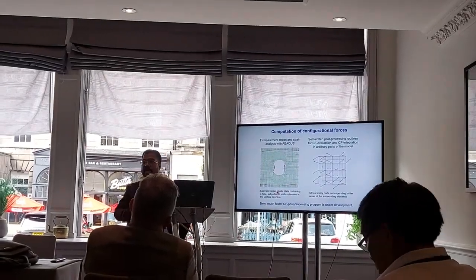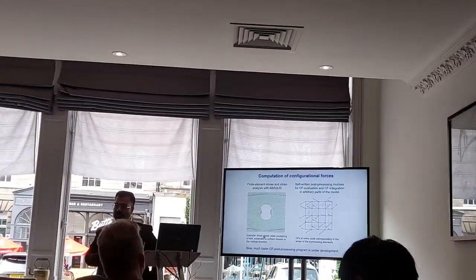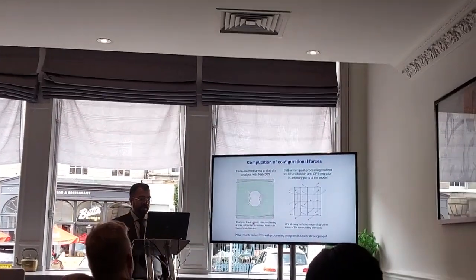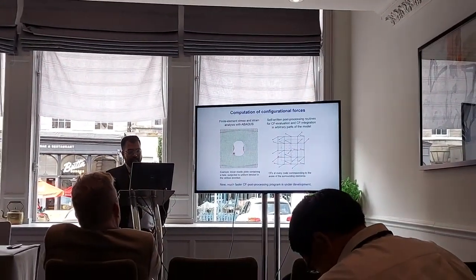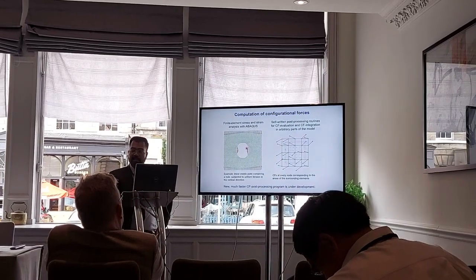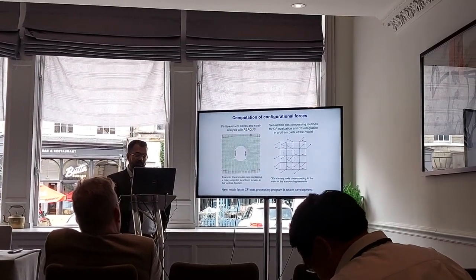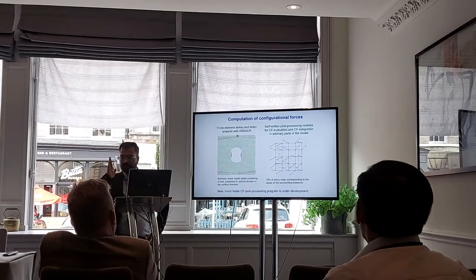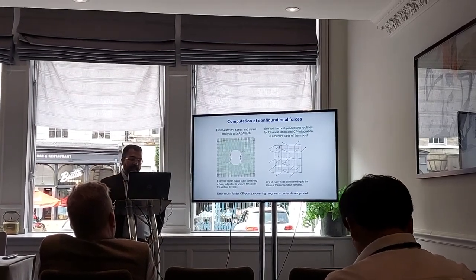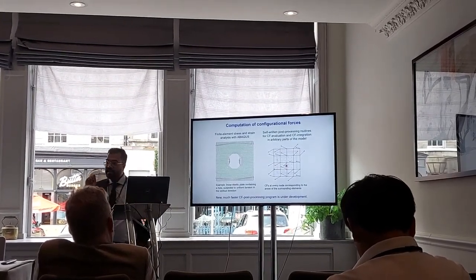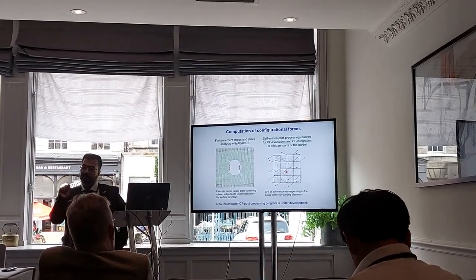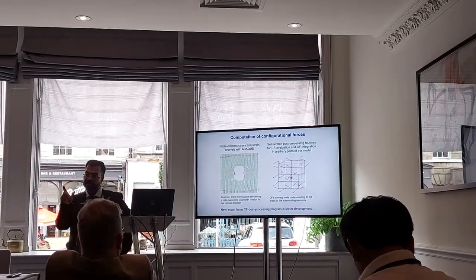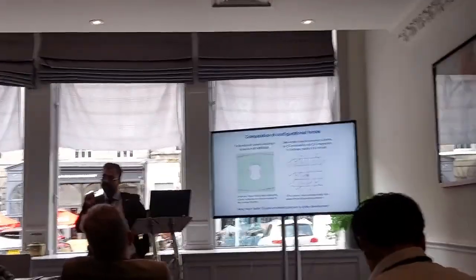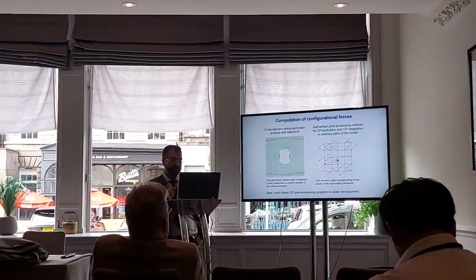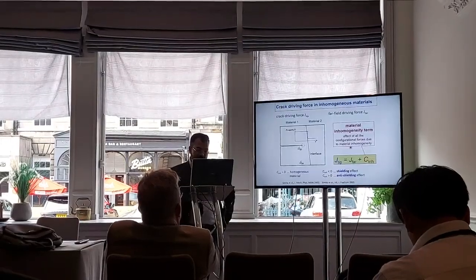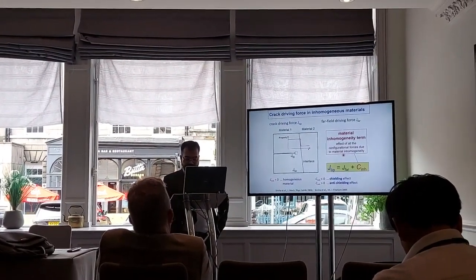We incorporate this by coding it in Python or other languages, and so if you have a hole like this, you get these arrows representing the configurational forces. You also have configurational forces at the surface because there is a transition from the material to air, and this has a dependency on the element size. So if the element is distorted, so if it is not square, there is a problem. So you need to keep the elements in a square shape, and from that we calculate this.